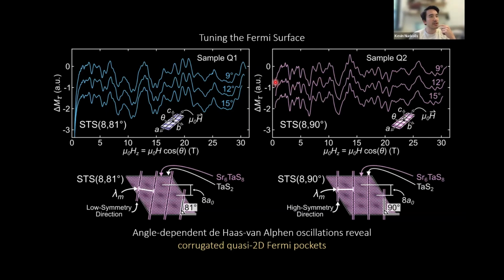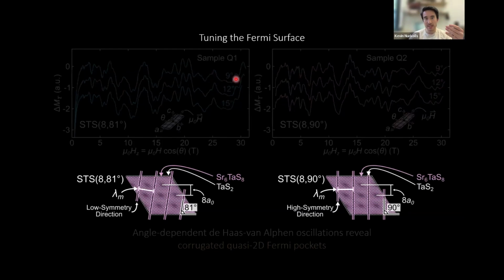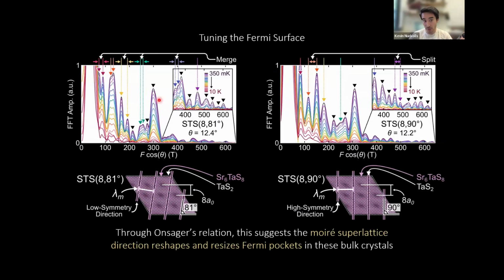Onsager would suggest that we try to make this statement a bit more quantitative, because Onsager tells us that the frequency of quantum oscillations is directly proportional to the extremal Fermi surface area in K-space of that pocket. So effectively, the frequencies are going to give us the sizes of Fermi pockets. And so we Fourier transform signals like this, and we see that these Moiré metals have a dense cascade of low-frequency pockets, very small Fermi pockets in momentum space.